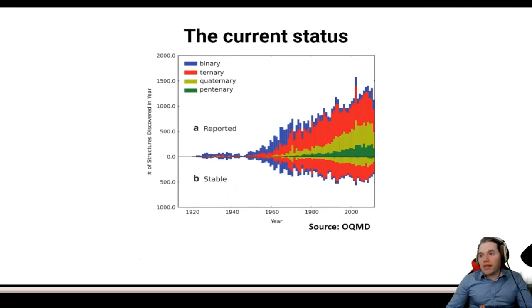So you can look a bit at the databases we have on existing materials. This is a figure from a few years ago. At the top here, you see the number of materials that are reported. And at the bottom, you see the same thing, but ones that are actually stable. So at the top here, there are also materials that were created under very high pressures, under some specific temperatures, that were grown on top of other materials. And in all these cases, they fall apart as soon as you remove them from these conditions. So if you look at actual stable materials, then you see that binary and ternary materials are discovered at about 500 per year. And quaternary are already like 300 or something, and we're actually going down here.